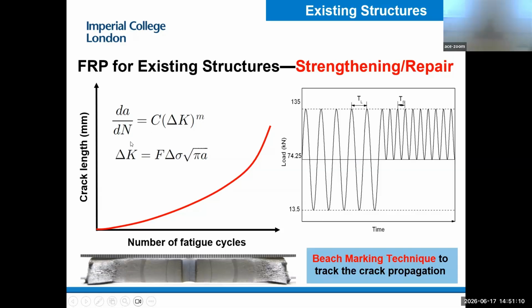Because this is the Paris law. Paris law is a semi-empirical model which can describe the crack propagation behavior. According to the Paris law, if you change the stress range, which is delta sigma, you will change the stress intensity factor at the crack tip, and you will change the crack propagation rate, the speed of crack propagation. So if you slow down the crack propagation, it will create a mark on the fracture surface.